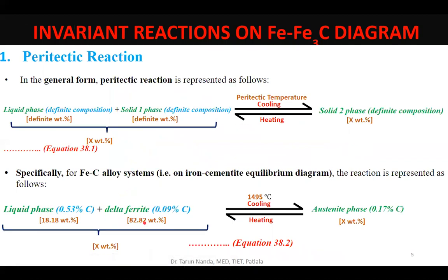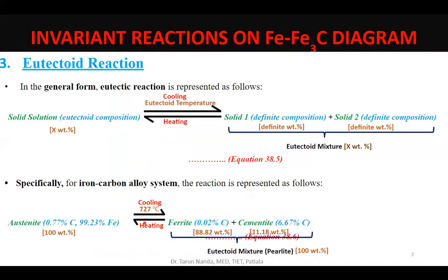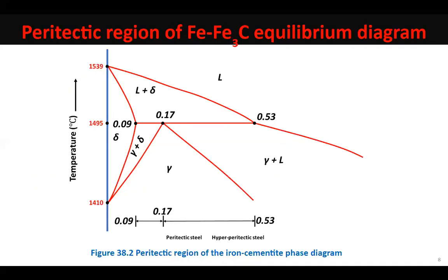and this weight ratio becomes 1:4.5. So that means whenever the peritectic reaction occurs in a materials system, the iron carbon material system, the liquid and delta ferrite will always react in the weight ratio of 1:4.5, and whatsoever liquid or delta may be present in an alloy, it is this weight ratio in which they will come forward and participate in the peritectic reaction and form the austenite phase. So what does that mean?